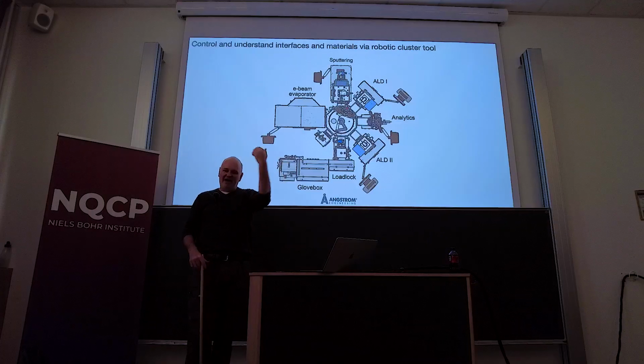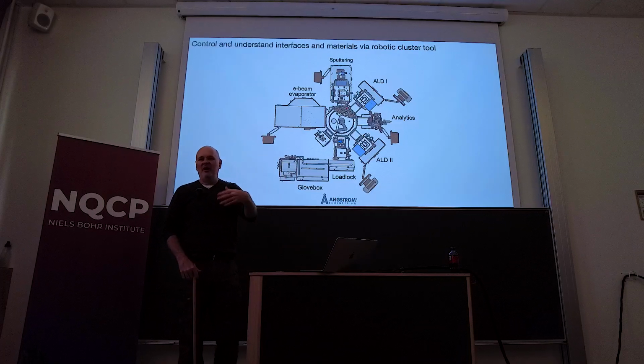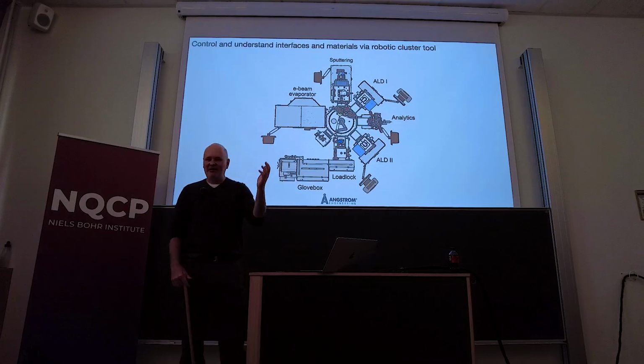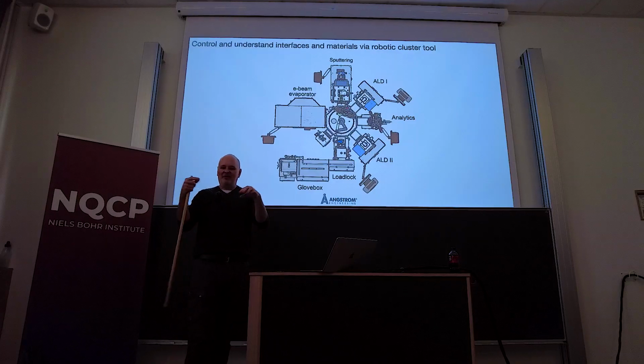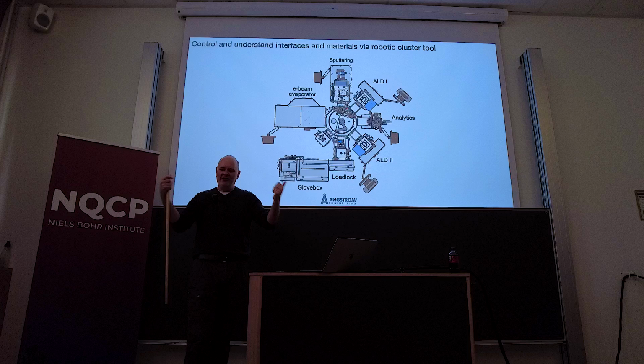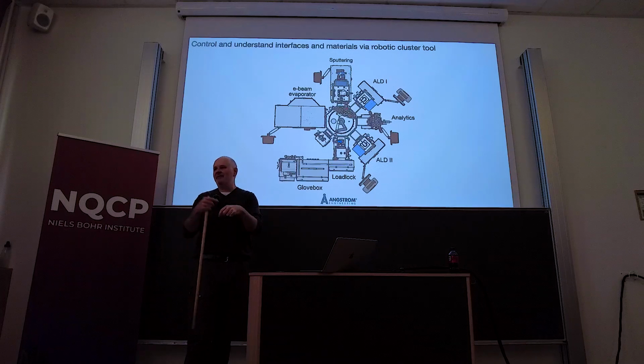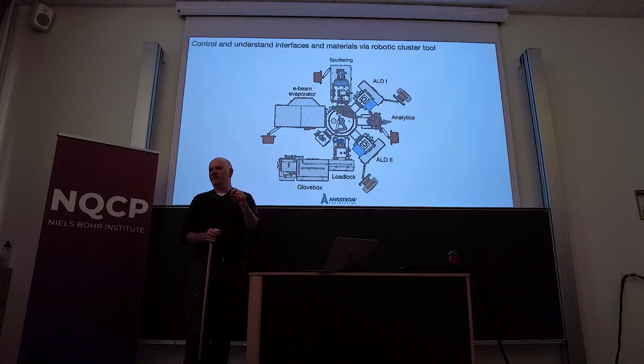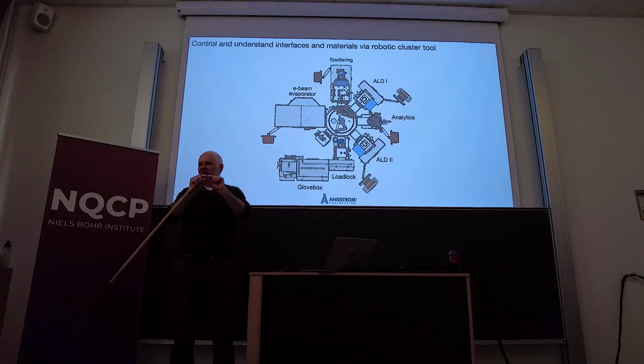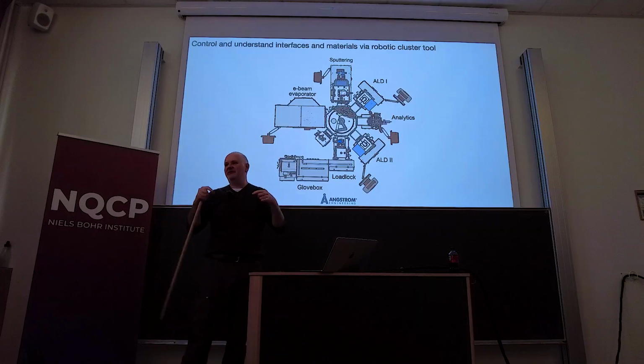And so you purge out the metal organics and you come in with water or oxygen plasma or nitrogen plasma or whatever, and that reacts with the organics that are sticking up off the surface. Those leave and you're left with a metal oxide, metal nitride, whatever. But what's left behind is much smaller than those golf balls. And so each layer, you're talking like half an angstrom to an angstrom of growth for every cycle. And that's less than a single atomic layer of the material.